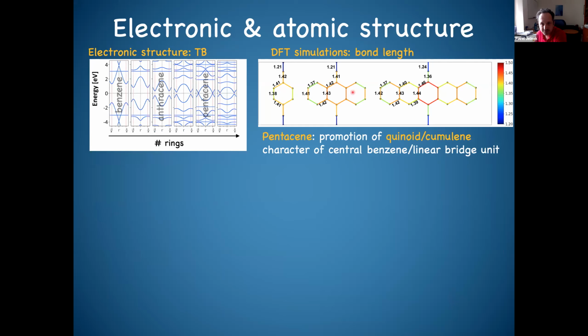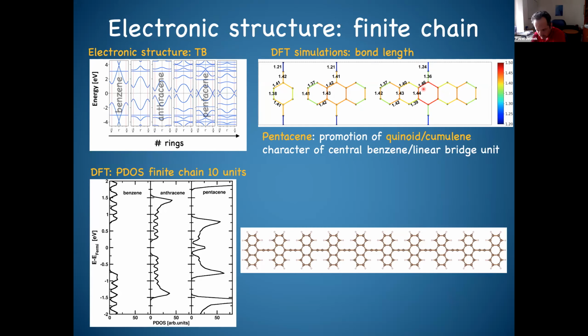Again, if I analyze the anthracene and pentacene, I see a strong reorganization of the bond lengths. Here you see that this triple bond, which had a shorter distance, now gets enlarged. But more interestingly, I can also see relatively large changes in the distances in this part. Now, I told you that if we go from this topologically trivial phase to the topologically non-trivial phase, one of the features which should appear is the presence of edge states. So far, all the calculations have been done on a finite system.